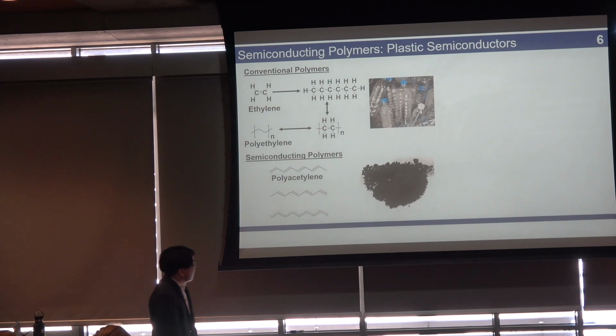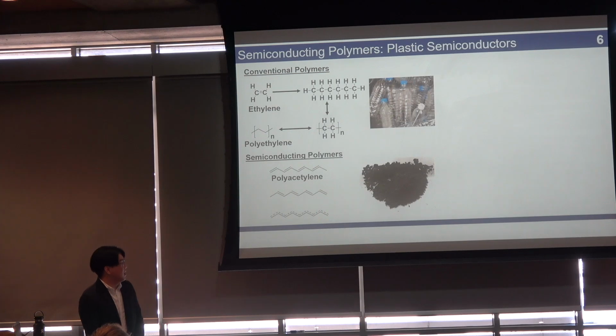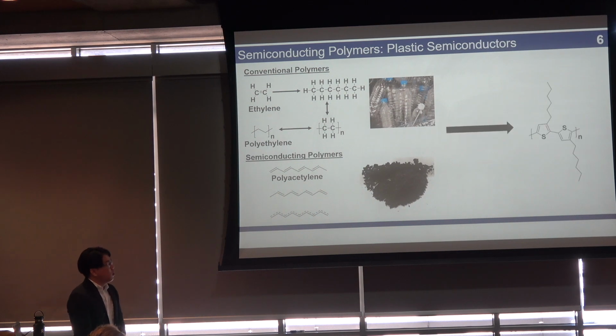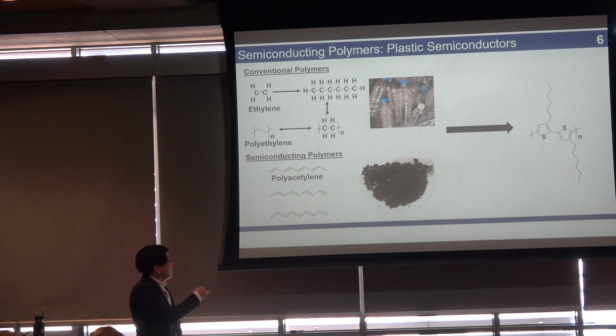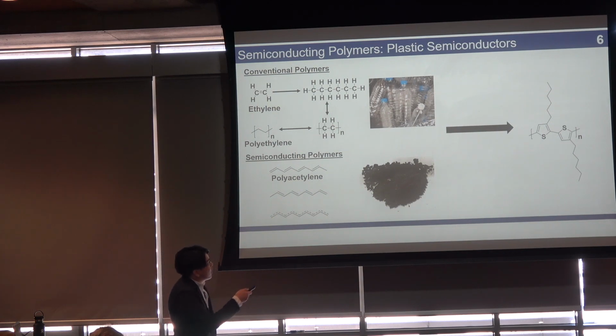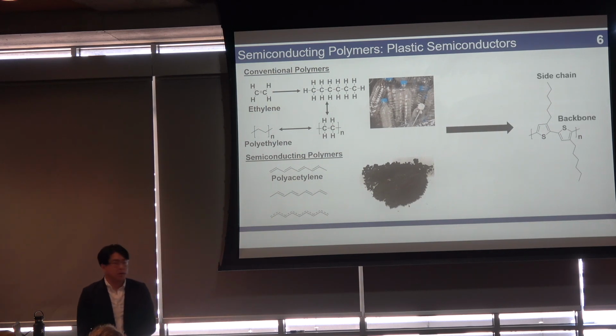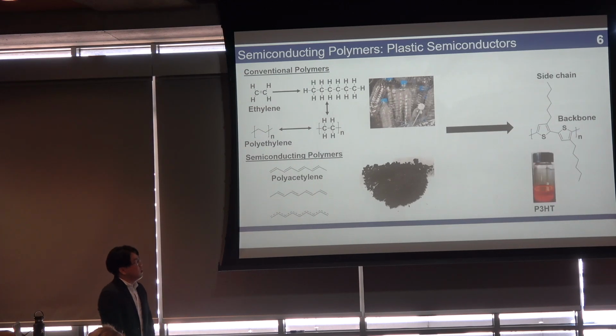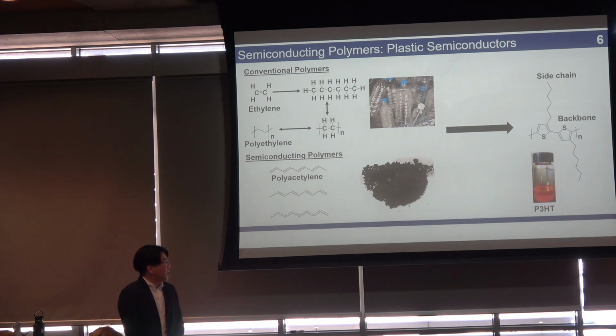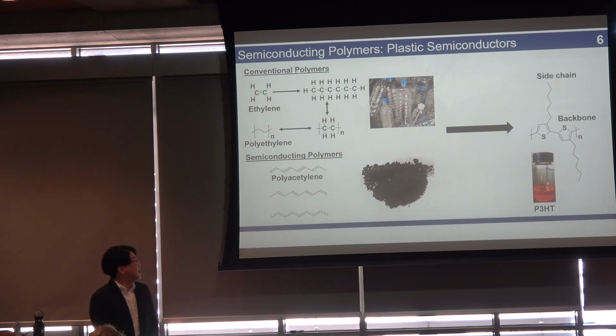The problem is these polymers look something like this when they're synthesized. It's polyacetylene. It's basically brick dust. It's not usable in this form. So to make them more usable, instead of taking this purely conjugated structure, we can add these aliphatic alkyl side chains to increase the entropy of solution. What you can do then is dissolve this into organic solvents, and you can use it as is.